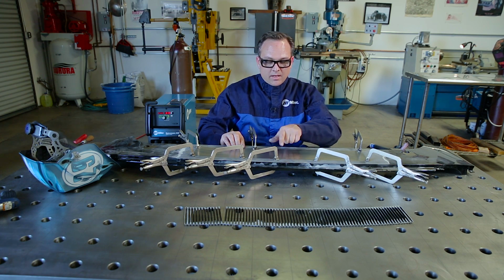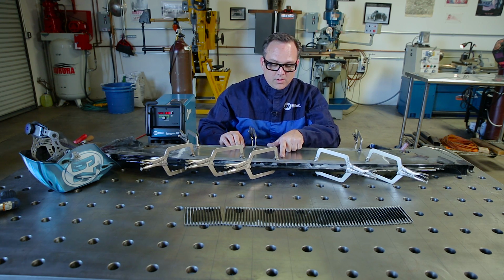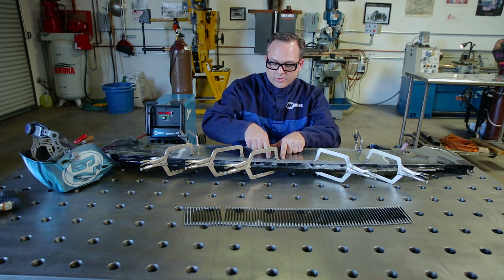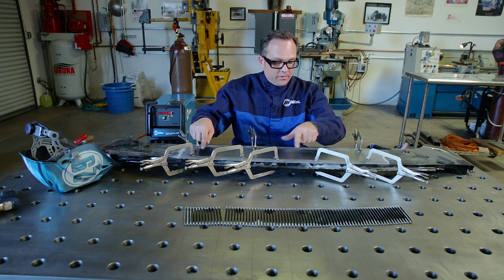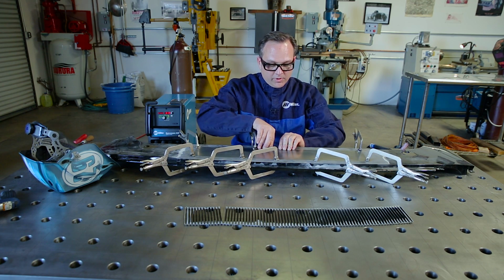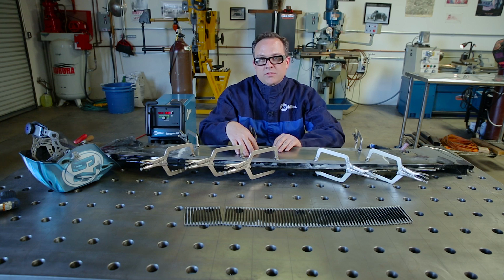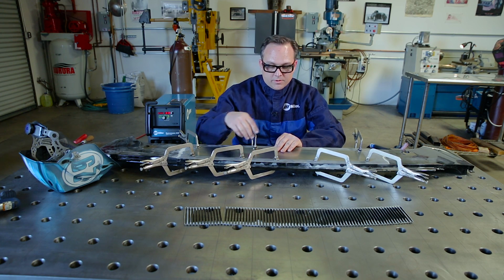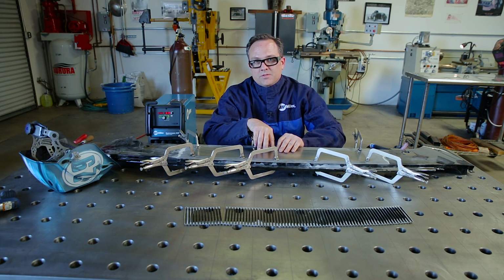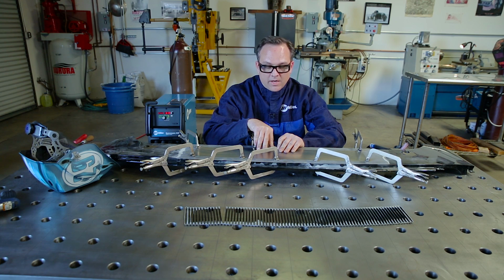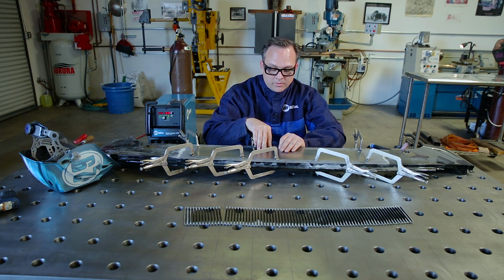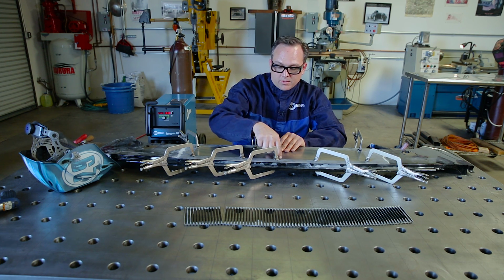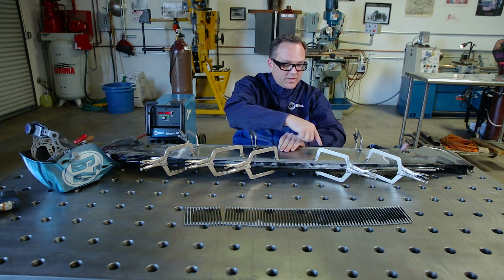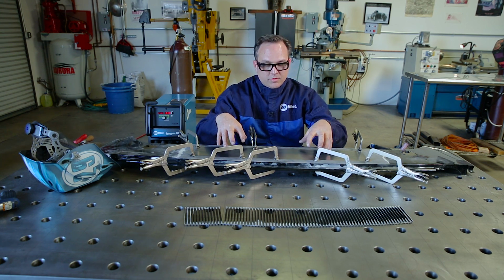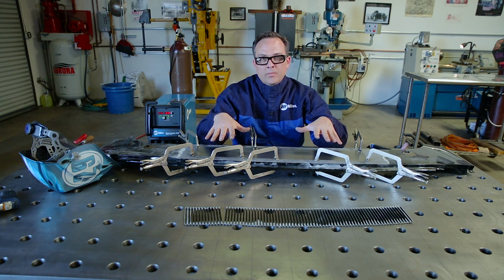And when I start to tack, I'm gonna start in the middle, and I'm gonna tack about every 3/4 of an inch, and I'll work my way out and work my way around completely. One mistake I've seen a lot of people do is they'll tack, and again, this is something that's kind of unique to me that I've figured out on my own, but if I start tacking different places around, it creates stresses in it, which will wind up warping my piece.